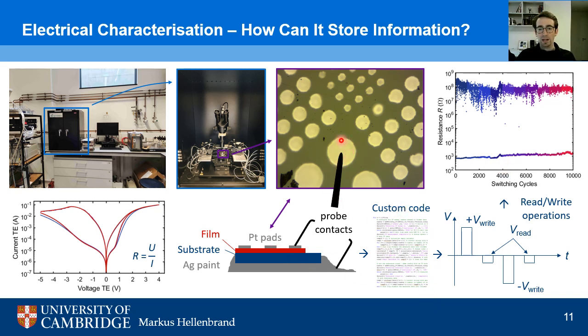We do this by applying a voltage to the top contact here, as I mentioned. Often this is realized by a custom-written measurement program, and the way that a computer operates is by putting a short positive pulse or a short read pulse to one of the contacts. So we try to do the same in our measurements. We apply, let's say, a positive write pulse. So in the IV curve, this would be somewhere here. We switch the state, and then with a very small voltage, we measure what state the device is in at the moment, and then just repeat this tens of thousands or millions of times.